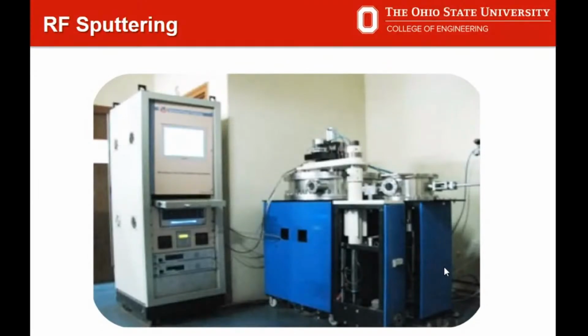During my PhD, I mostly used sputtering. Sputtering is a technique where you bombard the plasma ions onto your target. The target is the material that you are going to deposit on top of your substrate. By creating these plasma ions, you are continuously bombarding, with ions from the plasma hitting the material that you are going to deposit. Finally, that will be deposited on top of the substrate. This is a very economical system, which is why people use this kind of technology.